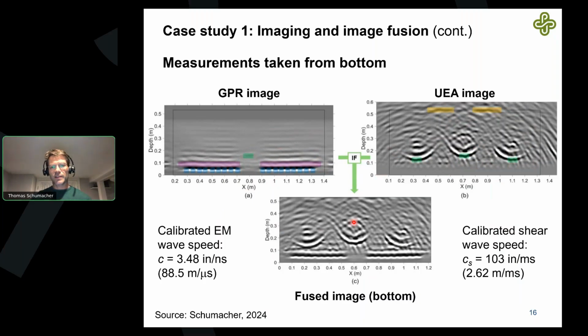Now we can fuse them together. I didn't spend any time explaining how the fusion works, but fusion could be as simple as just adding the two pictures together, taking the average, if you will. Sometimes I do that even in PowerPoint. I just put the two on top and then play with the transparency of one image to get a first idea. We use a little more complicated way, but we're basically merging these images via image fusion. And in essence, it could be as simple as just taking the average of two images. Images are just, in MATLAB language, if you use MATLAB, it's just two matrices, and you take the average of the matrices.